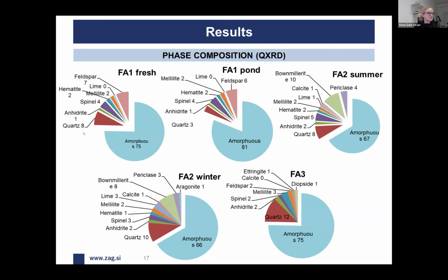The other thing is the presence of quartz, which is an inert mineral phase if we are talking about the pozzolanic latent hydraulic activity. It is the most evident in FA3, while in FA1 its quantity is relatively small.